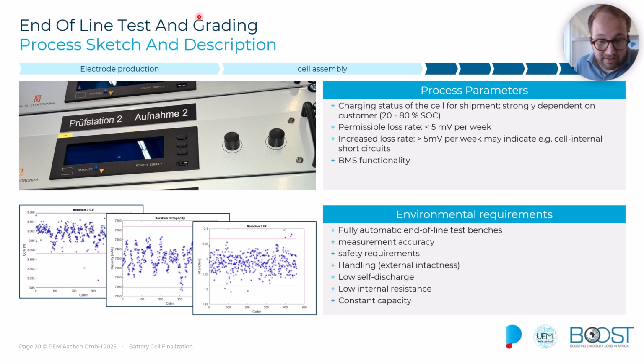A lot of mechanical inspections can happen, to ensure there is no swelling, the dimensions of the battery cells are in spec, there's no damage of the terminals, and the thickness of the pouch cells, for example, is still correct, and you can ensure that there is no swelling happening above the specification you defined. And also you want to make sure the sealings, for example, of the pouch cell still look good and the foil is not impacted.